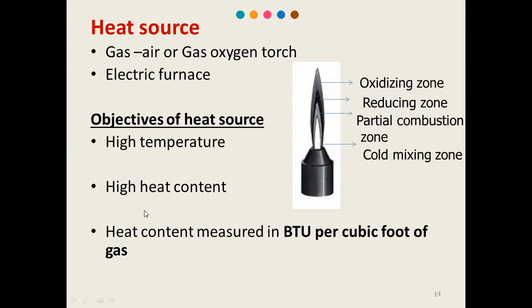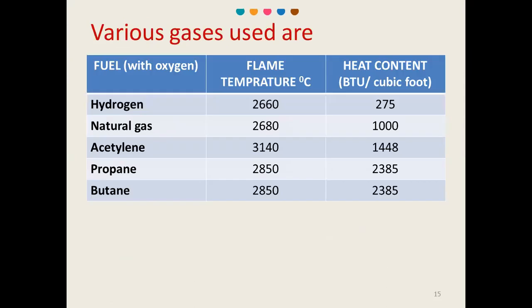If the heat content is low, the soldering time required is much longer and there is a danger of oxidation. So the heat content of the flame should be high, and this heat content is measured in BTU, that is British Thermal Unit per cubic foot of gas. Now let us see what are the different gases that are used. Now you can see there are hydrogen, natural, acetylene, propane, and butane gases, but which should be used? Here you can see the hydrogen has a flame temperature and heat content that are very low as compared to the other gases.